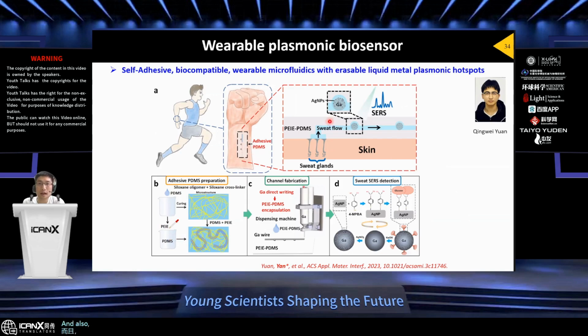And also, inside the microfluidic channel, there are gallium droplets here, and we can generate the silver nanoparticles on the surface of the gallium droplet. And also, we decorate the silver nanoparticles so that they can capture the glucose molecules in the sweat. So you can see the sweat can come into the channel, and the glucose will be selectively captured by the SERS hotspots. So we can do the SERS measurement and measure the concentration of glucose in sweat.